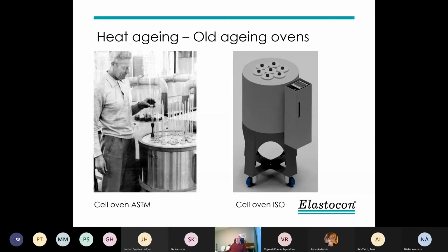And of course, you needed a huge aluminium block because in the old times the temperature controllers were not so accurate as today. To the right, you see a slightly more modern, but still an old design. It's a cell oven with bigger cells and controlled air exchange by an air pump. And there are 7 cells, and you can have one material in each cell. But even here, there were some problems with the accuracy. The problem with that type of oven is the preheating of the air. So the air was a little too cold when it came into the cell.